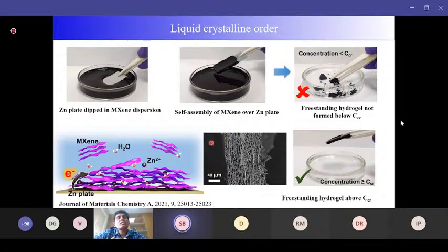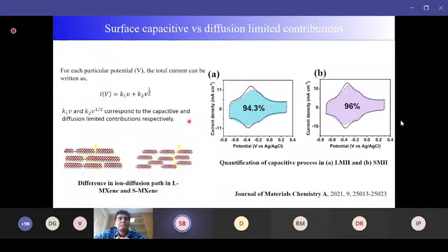So this critical concentration is size dependent. We have found that for the larger size MXene sheets, above 40 mg per ml, we can get freestanding hydrogel, and for smaller sheets, we have to go above 60 mg per ml. Then only we can get the freestanding hydrogel.